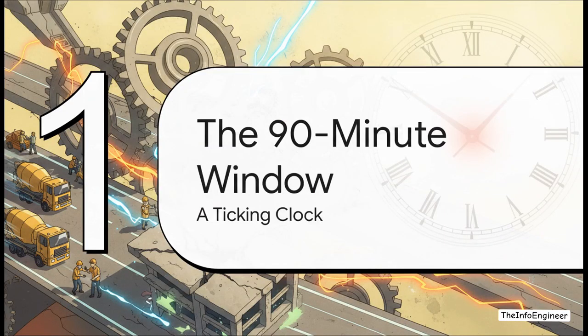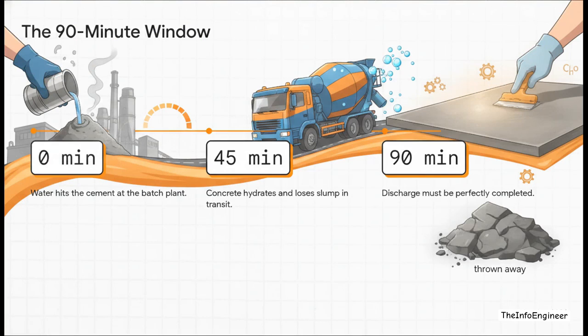To prevent that disastrous cold joint from happening, the entire construction industry is forced to operate under one incredibly stressful, immovable constraint: the 90-minute ticking clock. Right from the very moment water hits cement at the batch plants, ASTM standards dictate that you have precisely 90 minutes. That's 90 minutes to deliver, place, and finish the pour. That is a razor-thin window for the entire logistics chain to do its job perfectly. If you miss that window by even a little bit, the material starts turning solid and is completely unusable. It literally just becomes garbage that has to be thrown away.